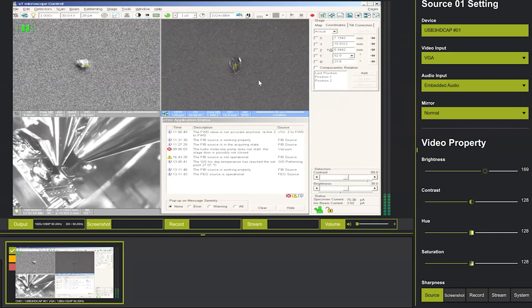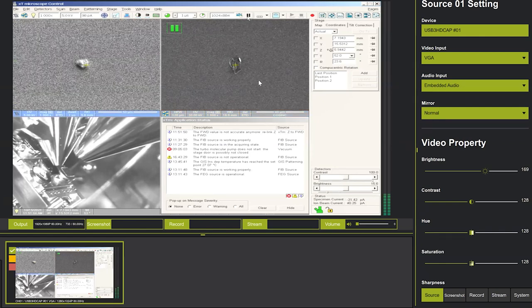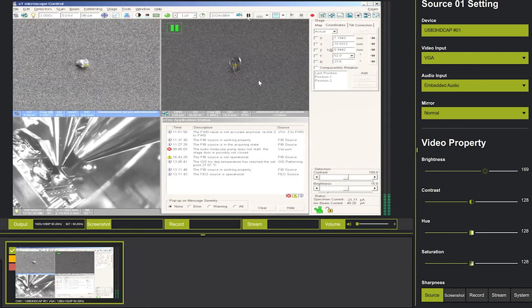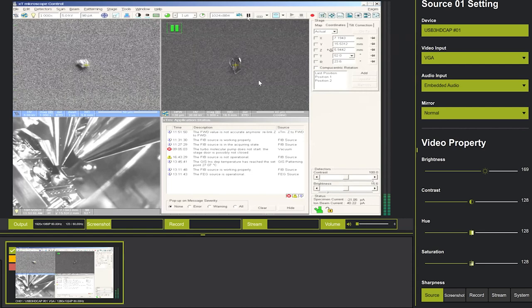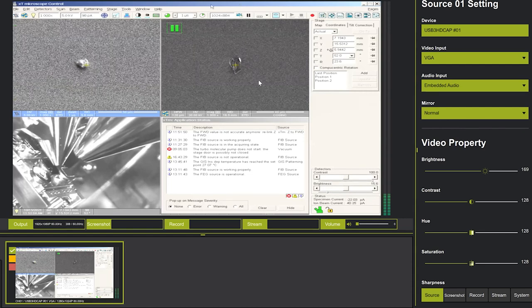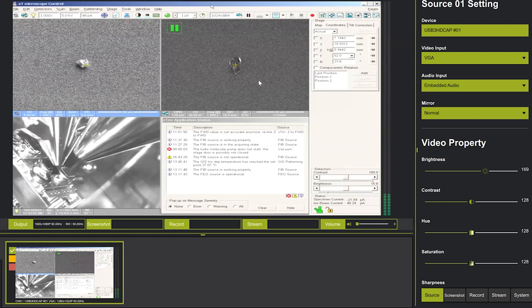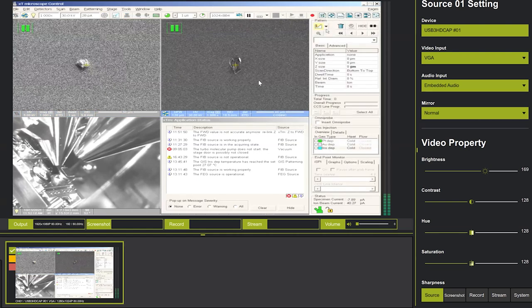That means I'm going to stop here. When I go back to the electron beam image, okay, two beams are hitting approximately the same area, the same spot. So I use the beam shift to align two beams here instead of the cross-section. Good. You can make a smaller one. 0.5 micrometer. How long does it take?